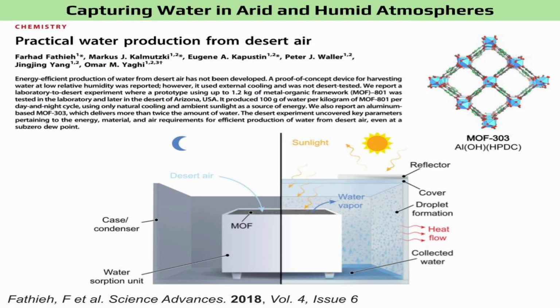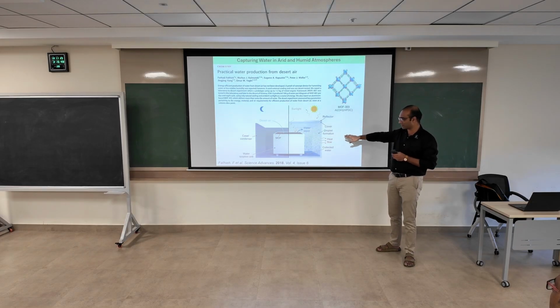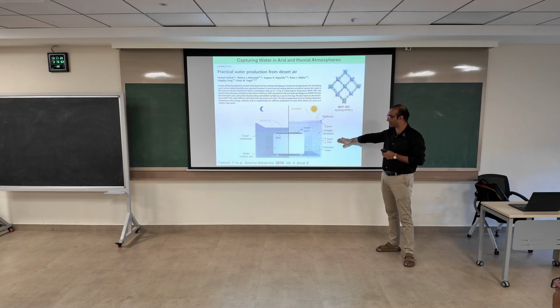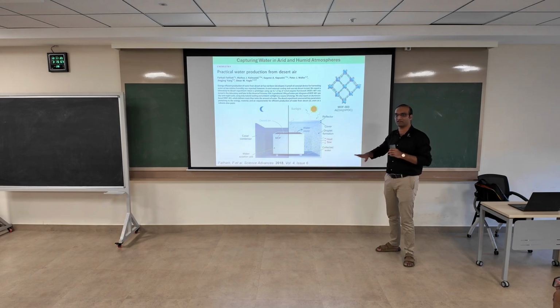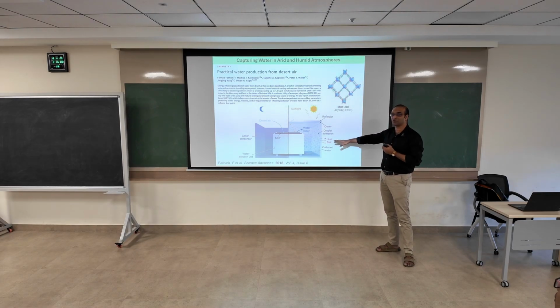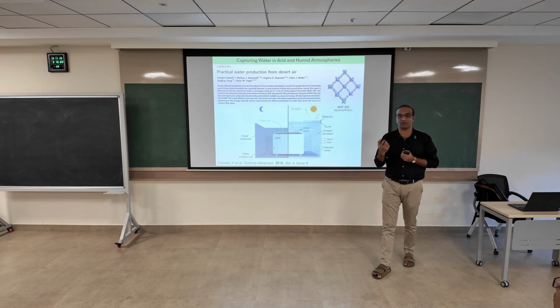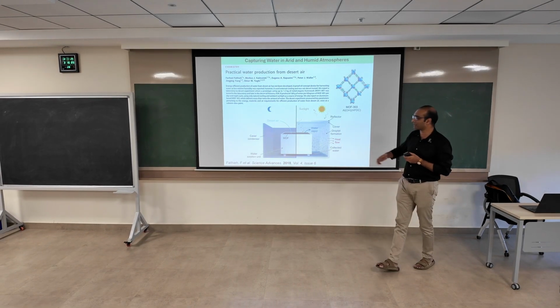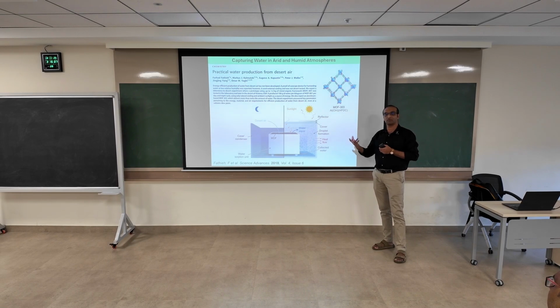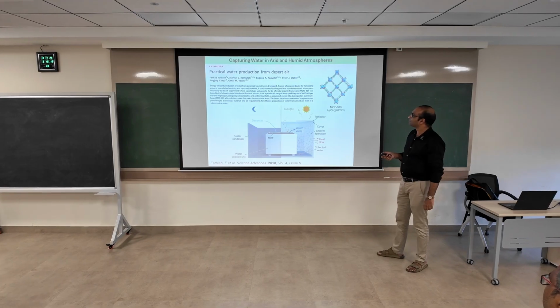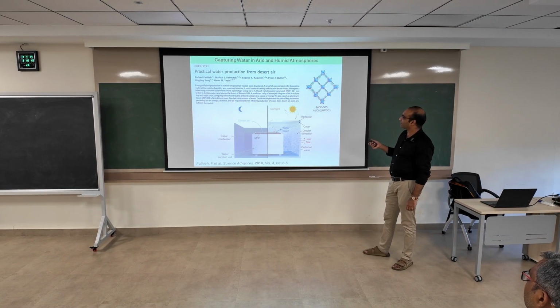Right? So this is the last application I'll show of MOFs. Most of the work that I've shown you here is actually a direct consequence of the work carried out by Omar Yaghi. This particular paper also, he was a big fan of this, he wanted to do this very extensively. He's gone to many desert locations in America and even in Saudi Arabia and other places, where they've tried to show MOFs as a source of capturing water from low humidity areas. Like I told you, there are MOFs which can capture gases, and there are also MOFs which can capture moisture from the atmosphere. Okay. So in this particular case, there's this MOF called MOF 801.